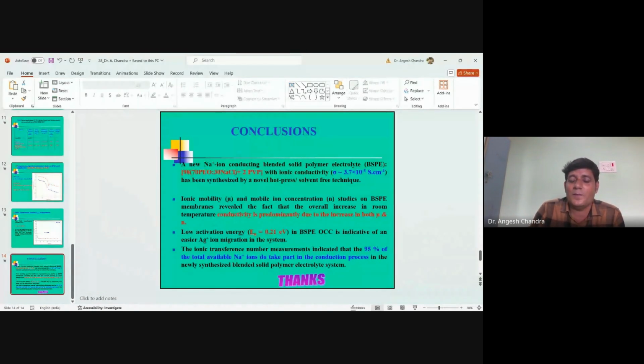And the ionic mobility and mobile ion concentration study of the blended solid polymer electrolyte shows the overall increase in conductivity is due to the increase in both ionic mobility mu and mobile ion concentration. These two ionic parameters are responsible for the overall increase in conductivity. The lower activation energy, 0.21 electron volt, in the blended solid polymer electrolyte is indicative of easier Na plus ion migration in the system. There is a typing mistake here, it is not silver, and this is the Na plus ion migration in the system.